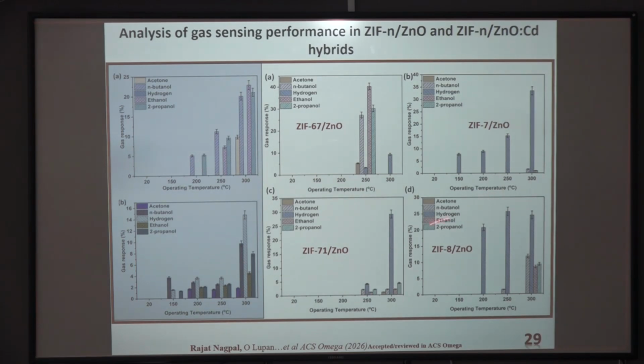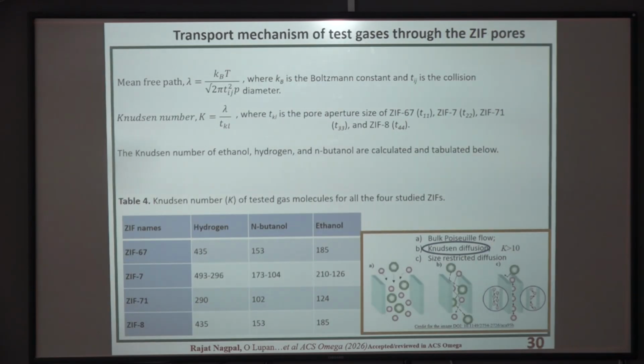And among other hybrids, here we can see appreciable selectivity for hydrogen, and among VOCs for n-butanol and 2-propanol, which is quite good. And about the transport mechanism, calculation of the Knudsen number using mean free path comes out to be more than 10 in all the cases, which means it falls in the Knudsen diffusion regime.